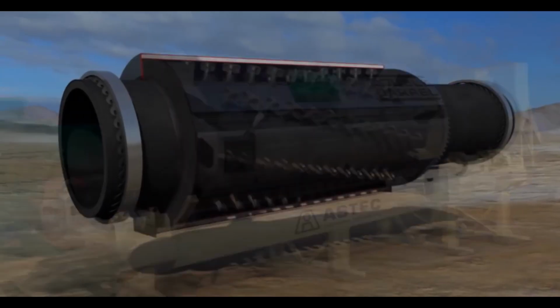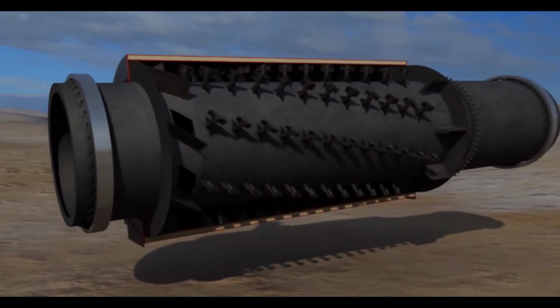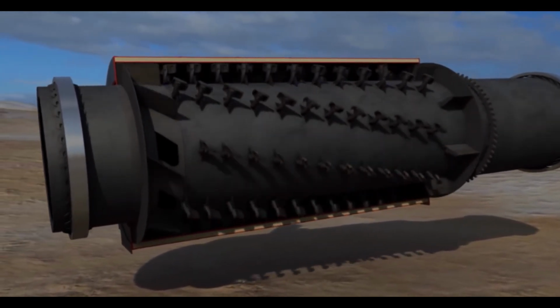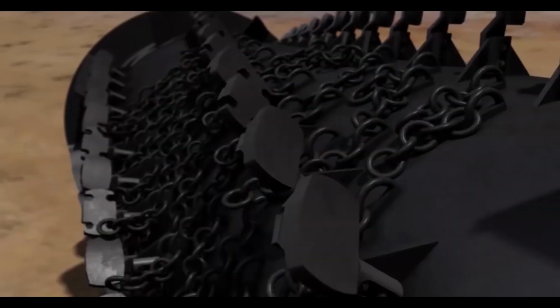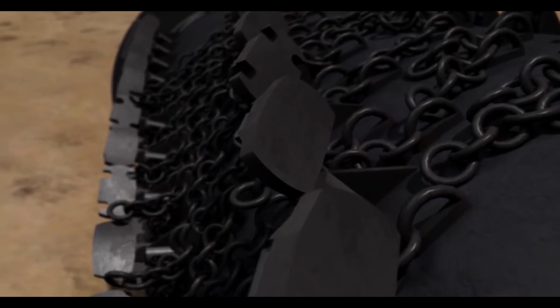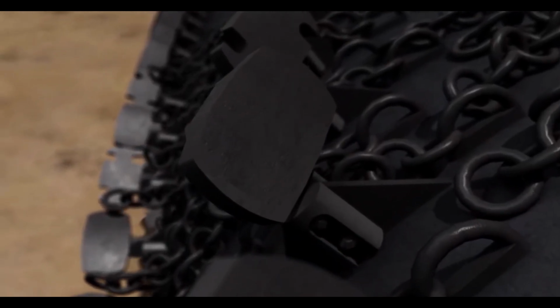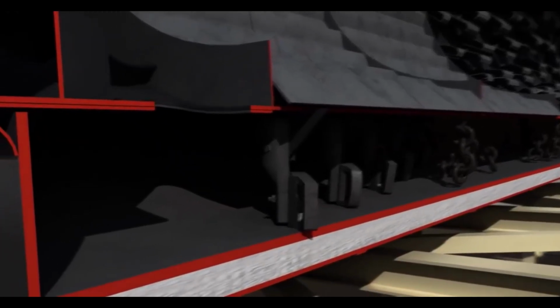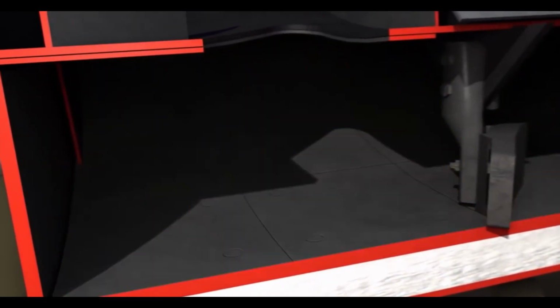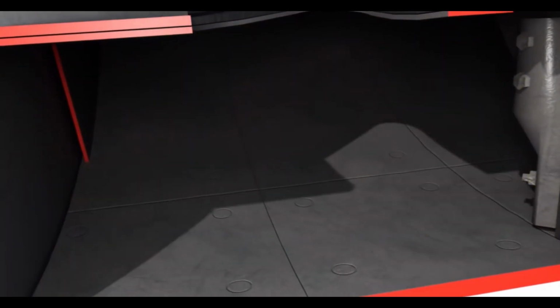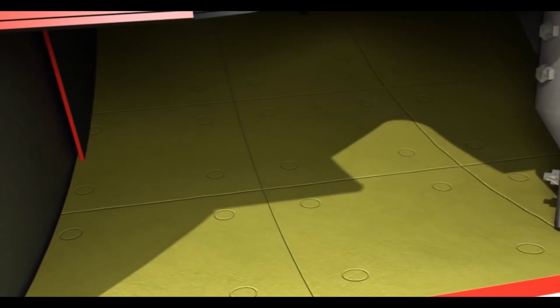The mixing chamber includes rows of mixing paddles mounted on the outside of the rotating dryer drum. These paddles ensure thorough coating of the aggregate. Nyhard paddles mounted to the outer surface of the drum convey and mix the heated aggregate with RAP, AC, and dust. Nyhard belly liners provide a wear-resistant surface for the mix to slide across as it travels through the mixing chamber to the discharge chute.